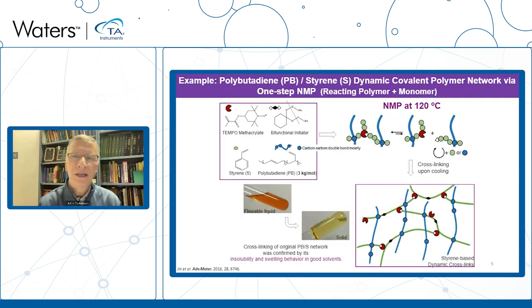And here we are sort of drawing an analogy to rubber tires. Rubber tires are often made from copolymers of styrene and butadiene. And here we're producing a material where we are reacting polybutadiene, in this particular case, low molecular weight polybutadiene, just 3 kilograms per mole, with styrene to make copolymers. We add in a small amount of a radical initiator and a very small amount of a molecule known as tempo methacrylate. This tempo methacrylate has a nitroxide radical on it, and these nitroxide radicals are stable radicals. They don't react with each other, but they do react with carbon-based radicals, and they are reversible bonds.